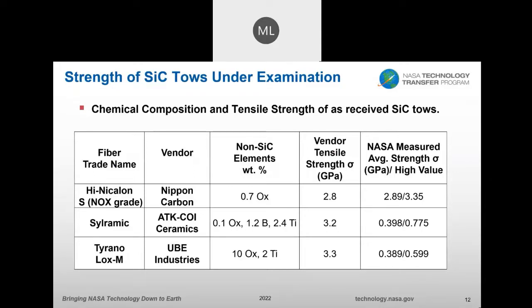Okay, so these are the three fibers that we looked at. They're from three different vendors. We looked at Hi-Nicalon S, Sylramic, and Tyranno. If we look at the non-SiC elements, we have 0.7% oxygen in the Hi-Nicalon S, and in the Sylramic 0.1 oxygen, 1.2 boron, 2.4% titanium. And then in the Lox-M, we have a high percentage of oxygen and 2% of titanium. The vendor-reported strength is 2.8 for the Hi-Nicalon S, 3.2 for the Sylramic, and 3.3 for the Lox-M. The actual strengths that we measured in the samples that we had: Hi-Nicalon S measured as reported by the company, whereas the other two measured approximately 0.4 gigapascals. Next slide, please.